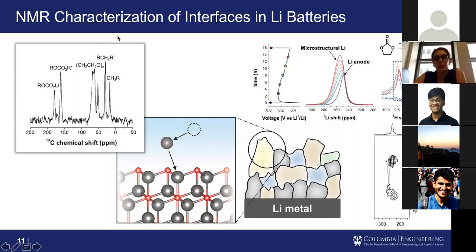This is showing a spectrum of what we get and the type of chemical resolution that we can get, so we can really assign what these chemical species are, what these electrolyte decomposition products are that form on the surface of our lithium metal, so that we can actually correlate electrolyte decomposition with lithium microstructural growth that we see in the cell. We can also start to learn about how lithium ions move through this layer, because with NMR, we can not only look at structure, but we can also look at dynamics. So we can assign all of the chemistry that's on the surface of lithium metal, and then also look at how lithium ions are actually being transported through here. So we can really provide a lot of molecular level insight into how these microstructures form, why they form, and how we can prevent their formation in the first place.